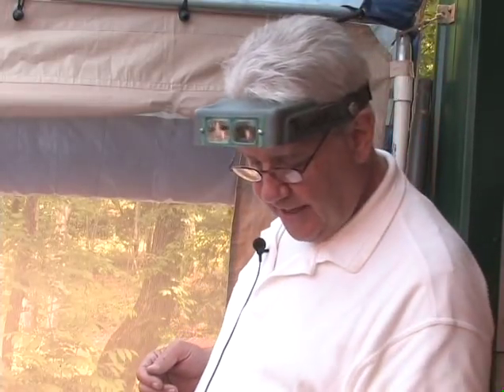Anyway, I've got some plastic punches that I use too, and it's a very resilient plastic, and it acts a lot like the chopstick does. After I've used the soft punch to get it in place, I come back in with a brass punch with a flat nose on it, and I further flatten that area down, and you've got some pieces of gold that are coming up the sides of the walls. That's really easy to get rid of. All you do is you take a knife like this, and you just carve into this area, bring it in, and pull the gold off. It's very easy to do.